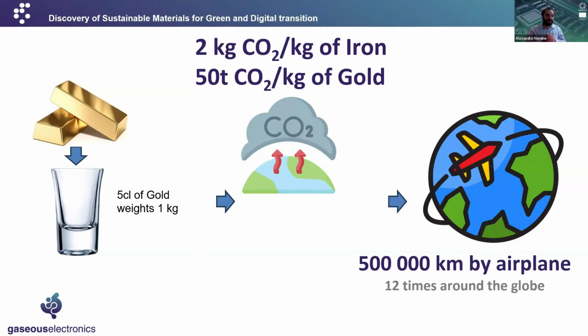So you see, there is some kind of consistency, but we should, once again, very much have this in mind. Gold is almost useless, I would say, for the green and digital transition, but platinum is not. Platinum is extremely important for the hydrogen economy and has a very similar CO2 footprint. So if you substitute 1 kilogram of gold or 1 kilogram of platinum by something with a low carbon footprint, as low as that of iron or aluminum, you will have made humanity save a few tons of CO2. This is where you can have a real positive CO2 footprint with your intellectual strengths, with your scientific strengths. So this is really important to keep in mind.